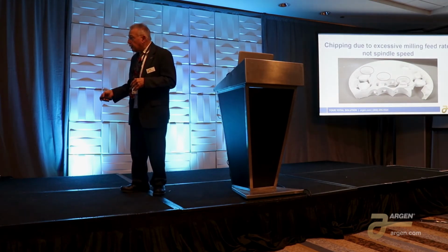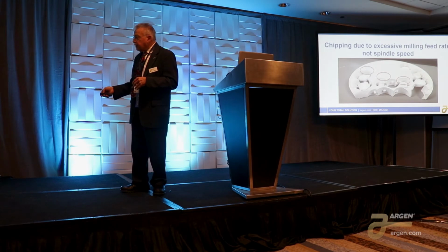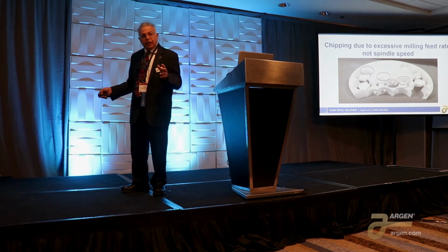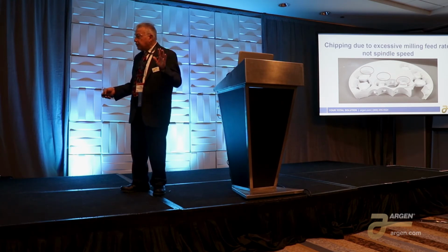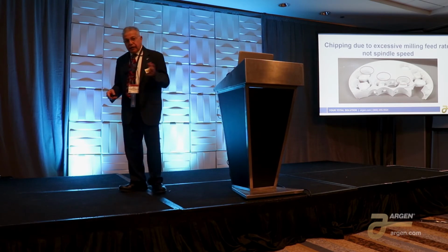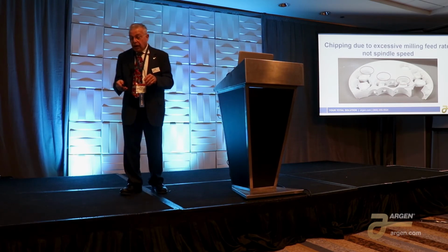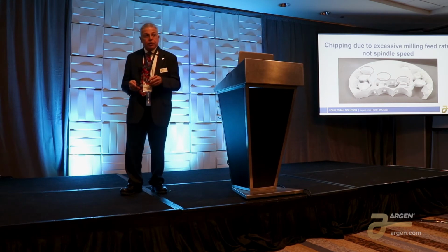Here you have a case I promised I was going to show you. Here you have chipping. This is the chipping during the roughing stage. The milling strategy was set for the ultra material, the very high strength material, and this is a high translucent material, so it's not as strong. And what's happened is it starts to chip where the roughing tool hits it first, and it chips all around. And the danger is when you have these implant parts, it'll chip right through it, and that'll render the part useless. So again, this is related to the feed rate, not the spindle speed.